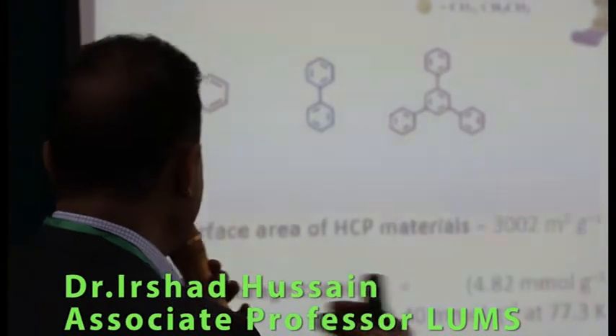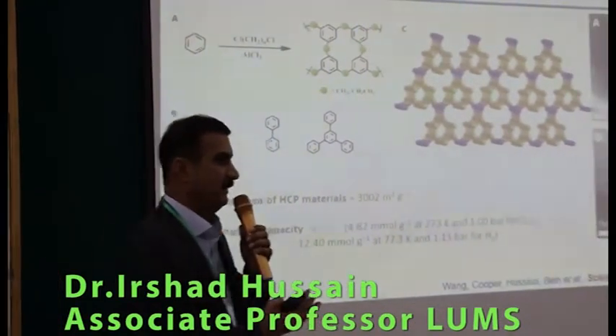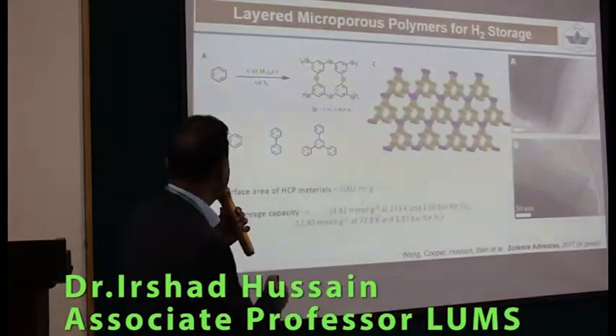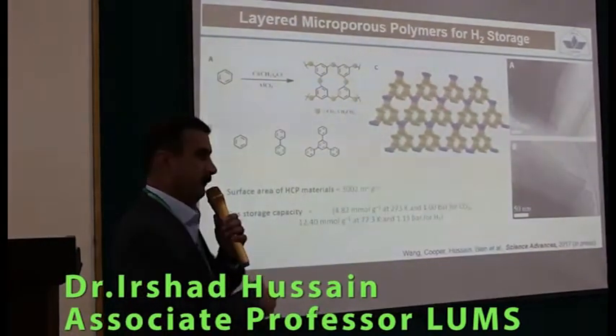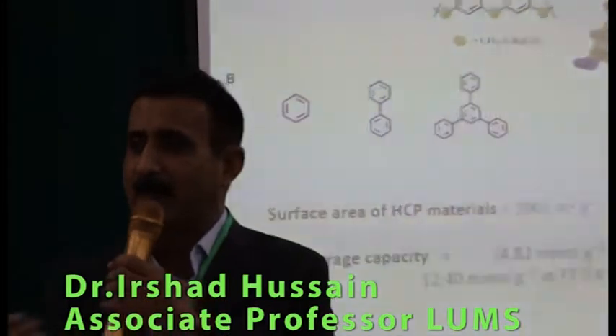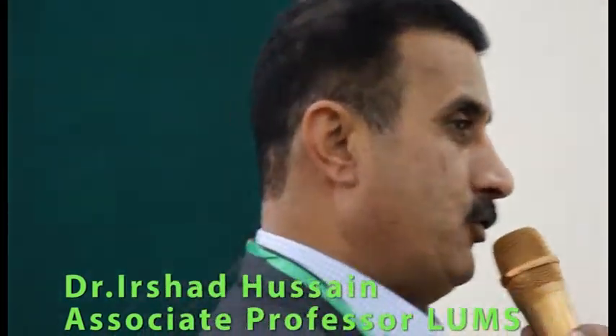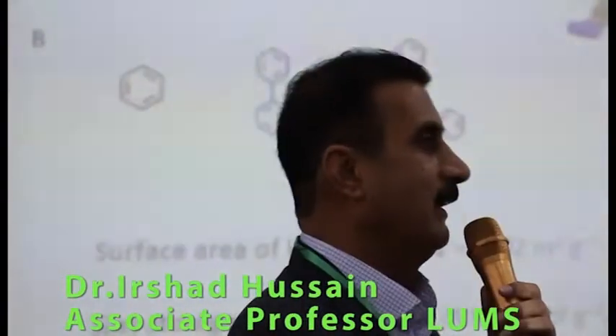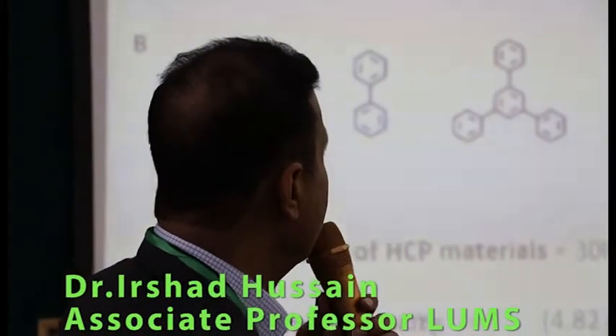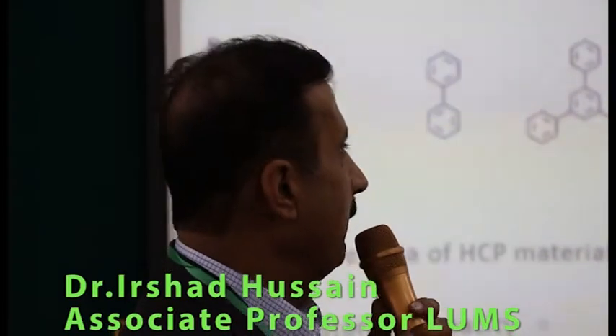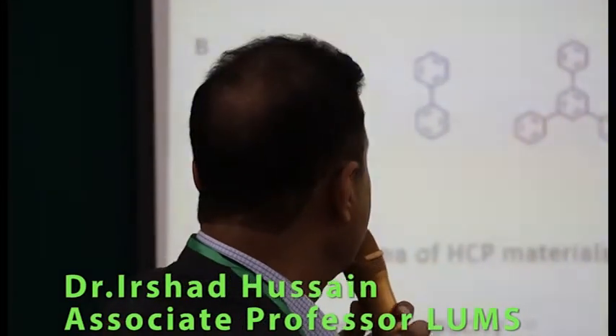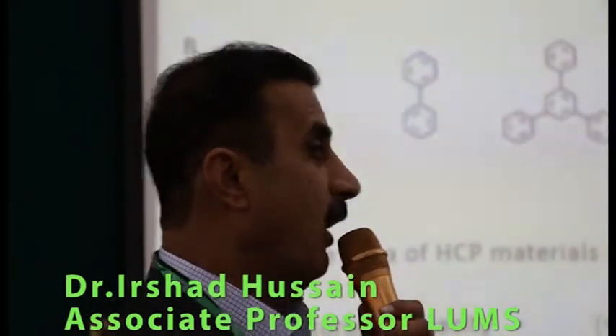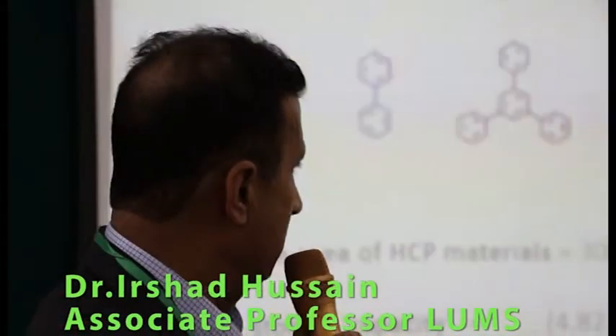So, another thing, we are also working on microporous materials. Here what we did, if there are chemists, they might have heard about the Friedel-Crafts alkylation reaction. And one of the limitations of Friedel-Crafts alkylation is polyalkylation, that you cannot really stop alkylation at a certain stage. So we made use of that Friedel-Crafts alkylation reaction to make polymers physically growing layer by layer on different substrates and having huge surface area, more than 3,000 square meters per gram. So this work was published last year in Science.